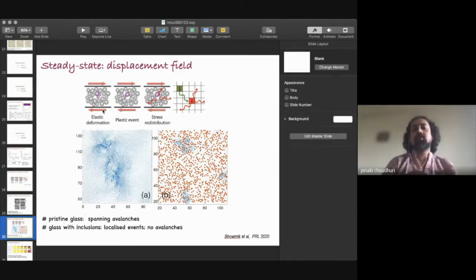So there is some local reorganization of this system, and then the stress is redistributed across the matter and other events kicking in, and so on. If I don't have these inclusions inside the system, what is observed are what are known as avalanches, where you have large-scale displacement fields emerging. On the other hand, if I include these inclusions, or the pinning sites, which are some kind of constraints on the motion, these avalanches are killed.